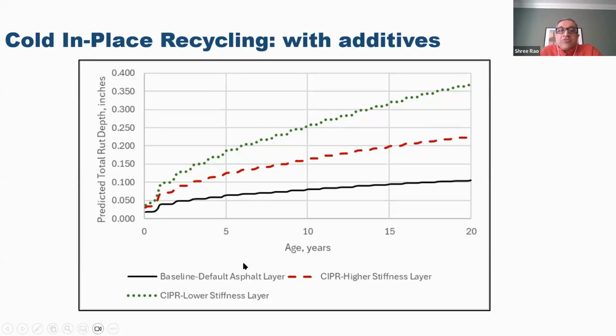So the default asphalt layer, so this is the new design, has a rut depth of about 0.1. Depending on the stiffness of the cold in place recycle layer, if it's a high stiffness cold in place recycle layer, you have rutting of about 0.2, and then when the cold in place recycle layer has a lower stiffness, you have a higher amount of rutting. So depending on how much additive you use, you can have different levels of rutting.